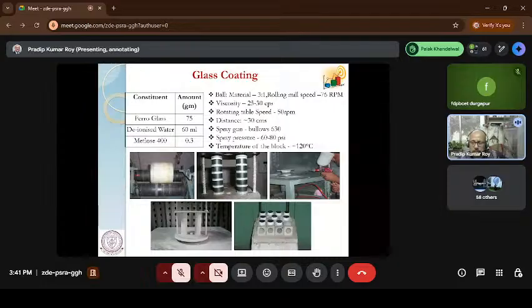So they mix the glass powder with some kind of binder system. It is basically polymer methylcellulose 400, and they optimize the viscosity, which is very much required to coat the block, around the varistor block. Again, everything you have to optimize, like what kind of pressure is required, what kind of viscosity, what kind of solid content, because we make a slurry. When I talk about slurry, there is a solid versus liquid ratio. Based on that, they optimize the slurry part also, and they coated it.